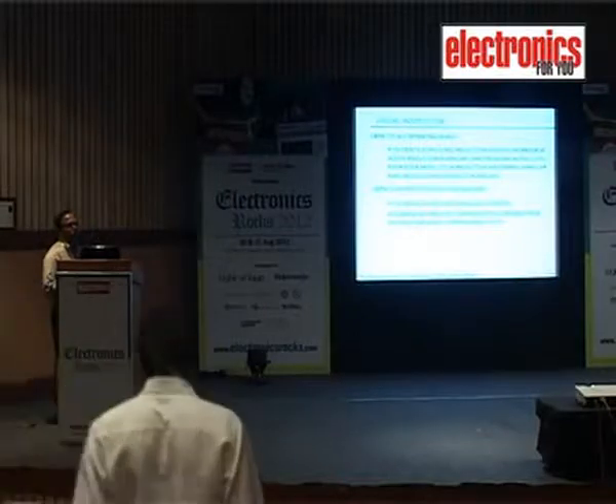And coming again to visual inspection, we find out defects in copper and traces. Like earlier in the laminates, we also critically view the copper, traces and pads for any pits, dents. Even a small nick is not acceptable in space grade PCBs. Small dents, because for a dent we cannot measure how much depth it has gone. With multi-layer boards this is more critical because the dent can protrude into the second or third layer, which can affect the performance of the PCBs. Then we also check for defects in protective plating, like the solder coating and solder mask coating over the pads. All such defects over the traces will come out while doing the visual inspection.